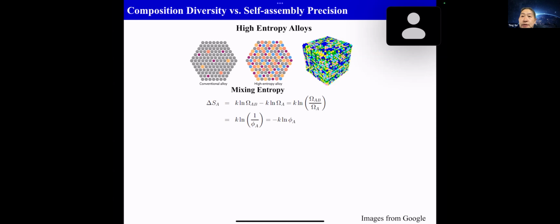And let me just start with what our hard material colleagues have been studying, these high entropy alloys. It's actually pretty simple. If you look at this equation, it's basically a copy paste from Flory-Huggins theory. So basically we're saying that as you start to increase the composition, the variety of the building blocks, your mixing entropy contribution to the free energy is going to increase substantially, especially as your phi A is getting really small. So each individual component is going to have its entropic contribution. By the time you go beyond one, two, three, four, actually for the high entropy alloy, by the time you go beyond five, a lot of new interesting phenomena come in.